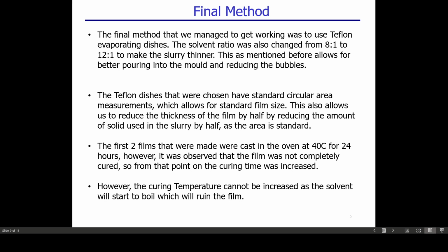The Teflon dishes were also chosen as they have a nice standard circular area, which allows for standard film size from batch to batch. When in the future we want to reduce the thickness of the film, we would simply reduce the amount of solvent used, as now the area is standard. And we're also in the future going to try to reduce the chance of the films sticking to each other by increasing the curing time so that we get a nice solid film.